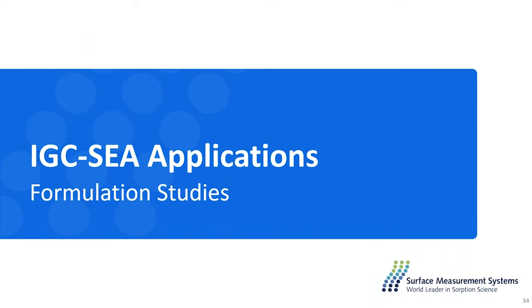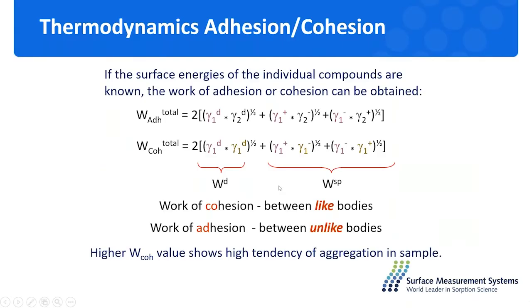And the next application for the IGC technique we can use is the formulation studies for the multi-component system. So we can calculate the work of cohesion as we introduced previously for the particles. So we have the dispersive surface energy from each component, and we also have the specific surface energy. And here for the multi-component system, we have the other component, so we can calculate the work of adhesion between unlike bodies. So we have the dispersive surface energy from solid 1 and solid 2, and we have the specific surface energy from two different solids as well.